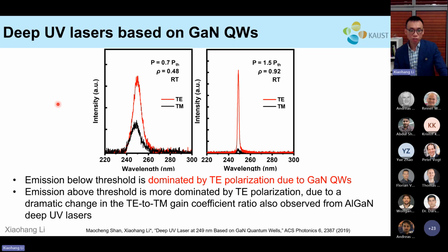In addition, I mentioned the transverse electric versus transverse magnetic polarization from gallium nitride, and this was verified by optical pumping below the threshold and above the threshold. Below the threshold, this is spontaneous emission. You can see that the TE dominates the spectrum because again, this is gallium nitride. If you have high aluminum AlGaN, the TM will dominate.